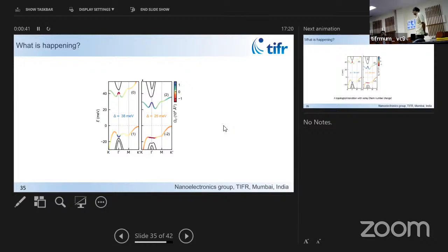Yeah, in your earlier slide, you mentioned that for this topological phase to be observed in the system, the time reversal symmetry should be broken. If you want a non-zero Chern number, you can also have topologically non-trivial states where one valley has a Chern number, let's say plus C. The other valley, if you don't break time reversal symmetry, will have a minus C Chern number. So the total Chern number is still 0, but it's topologically still non-trivial. So that's what the case is here. One valley and the other valley have opposite Chern numbers, but they still can undergo a topological transition.